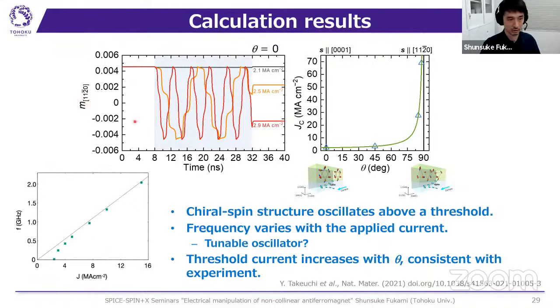This shows the dynamics of the residual magnetization as a function of time. As observed in the experiment, when the applied current is too small, nothing happens. But above a threshold, the oscillation is induced, and by increasing the applied current density, the speed of the oscillation also increases. This shows the frequency of the oscillations as a function of the applied current density. Below the threshold, nothing happens, but above the threshold, the frequency of the chiral spin rotation increases. This implies that this phenomenon can be used for tunable oscillators that can function at zero magnetic field, which is different from spin torque oscillators.